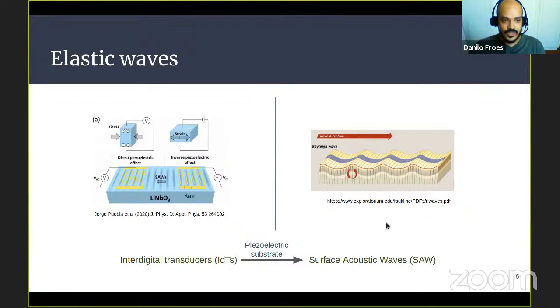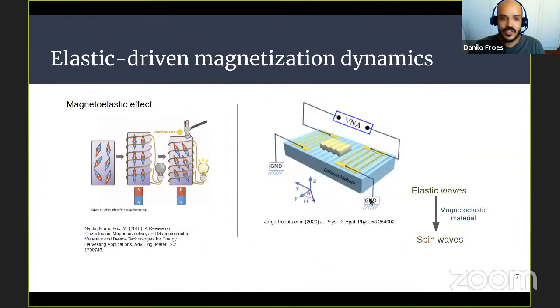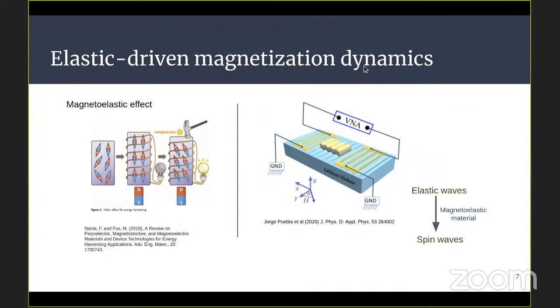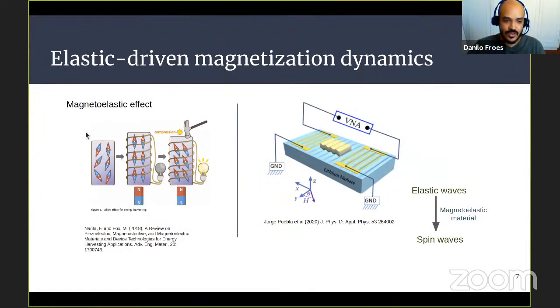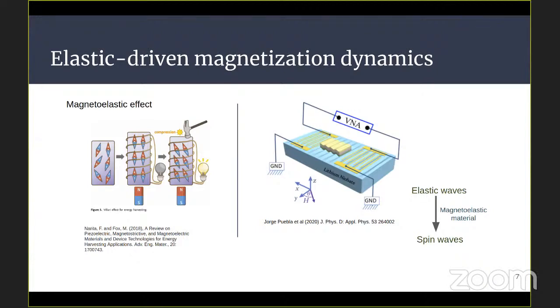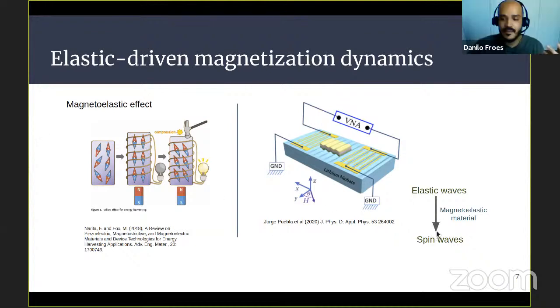The idea that has shown up in literature, it's not new, it's been for some time, is to couple these elastic waves to drive magnetization dynamics in magnetoelastic materials. With the magnetoelastic effect, you change the dimensions, you apply strain on the magnetic material, and the magnetic moments are deviated from equilibrium. By using materials that have a significant magnetoelastic effect, we can excite spin waves from elastic waves. So we have only a voltage-driven effect. We don't have ohmic losses here, so it's very energy efficient.